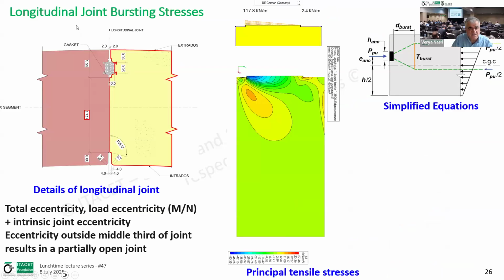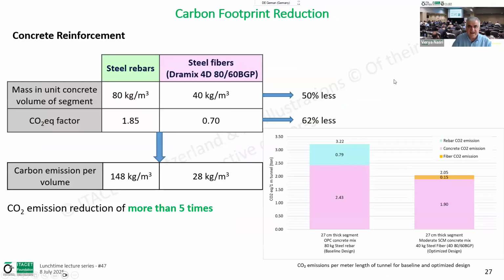So one load case is also longitudinal joint bursting. For this one, either we use a simplified equation from ACI or we use a 2D finite element. So this is very simple. We use a model here which is twice longer than the length of the segment. And with that, I get to the carbon.